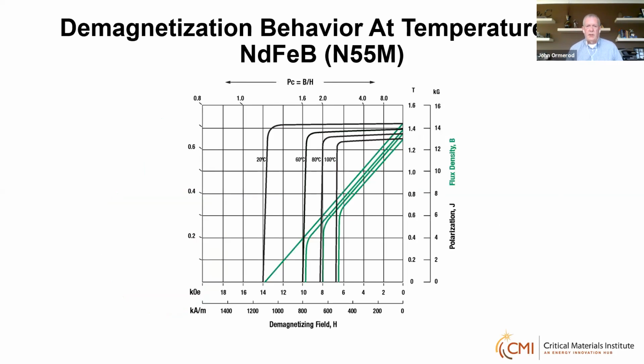I want to move on a little bit now and talk about one of the major disadvantages of materials based on the 2-14-1 compound, and namely that's their performance at elevated temperatures. So here's an example of the demagnetization behavior of a sintered neodymium-iron-boron grade N55M. And what you can see is the effect of increasing temperature in that it reduces both remanence and coercivity. And in fact, if you look at coercivity, we lose about 50% of the room temperature coercivity at 100 degrees C. Now, this is potentially a major issue in any application that's operating at elevated temperatures. For example, a servo motor that has to run at 100 or even higher temperatures.